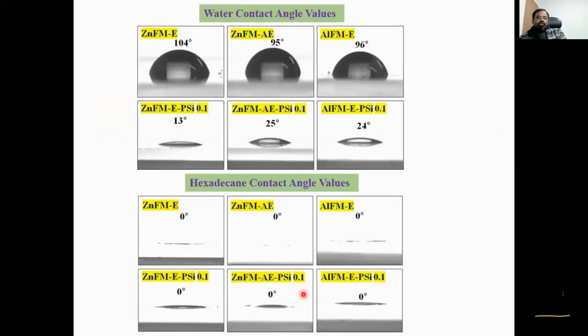And we checked the contact angle of that metal loaded substrate, and it shows around 100 degrees contact angle. And after the second layer of silica coating, it shows an almost completely wettable substrate, so hydrophilic to super-hydrophilic behavior. And we also checked the oil contact angle using hexadecane as an oil source. So it shows that it's completely wettable to hexadecane, and also to some other organic oils. So it shows some amphiphilic property after making these final coatings.